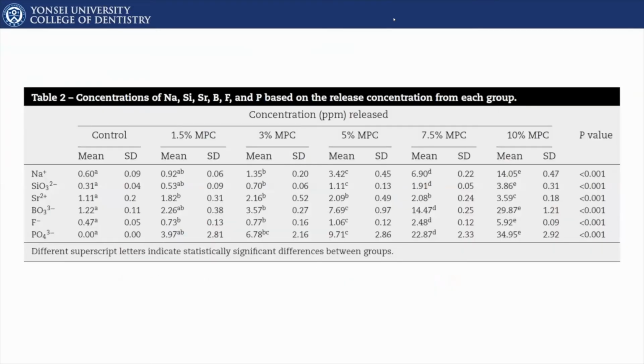But surprising results were found from this table. When we added the MPC and increased the amount of MPC in the composite, it was noted that if you look at this mean number, the amount of ion release for each ion is dramatically increasing as we increase the MPC amount. So this means that the ions from the glass ionomers, the ions from the SPRG, are for some reason released more into the matrix and then released more to the outside, where we detected them.